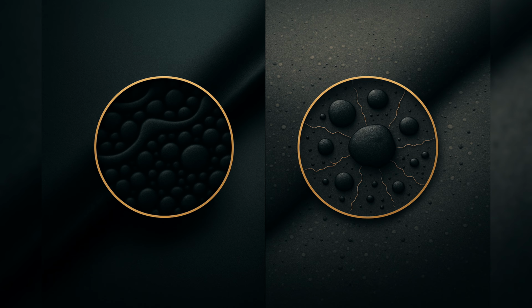Hardness, tensile, tear, dynamic properties, cure rate, scorch safety. Everything is affected. Carbon black is a classic example. When it's properly dispersed, it reinforces the polymer, raises modulus, improves abrasion resistance, and gives you a beautiful even surface.